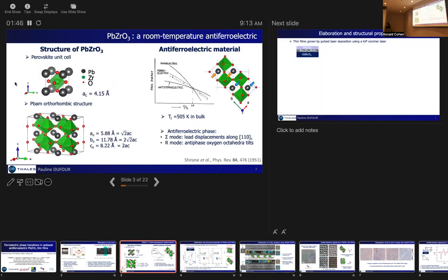So to explore these new perspectives, we focused on lead zirconate, whose structure is derived from the perovskite unit cell. It crystallizes in a Pbam or orthorhombic structure. And as you know, it's a room temperature antiferroelectric with a transition to a ferroelectric state around 505 Kelvin. Even though the mechanisms that rule this transition remain controversial, it is commonly accepted that this antiferroelectricity emerges from the softening of the Sigma mode and the R modes, which results in the lead displacements along the 110 directions. They are antipolarly aligned, and from the antiphase oxygen octahedral tilts.